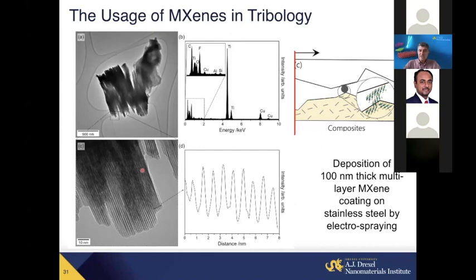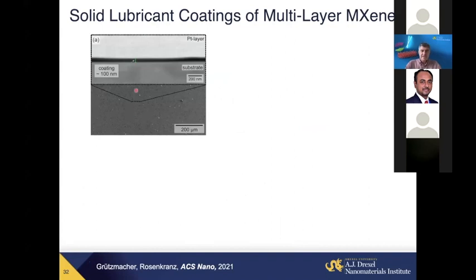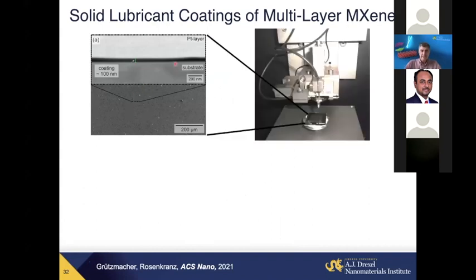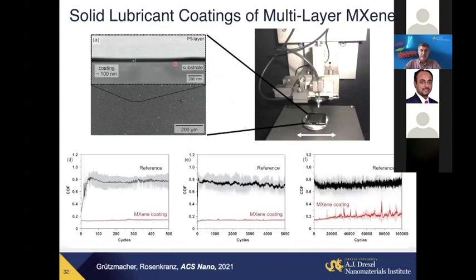So when they deposited 100 nanometer films on the surface of a steel substrate and tested them, what they observed in tribology was that the MXene coating drastically decreased the friction coefficient to about 0.1, which compares very well, I would say, with carbon materials.